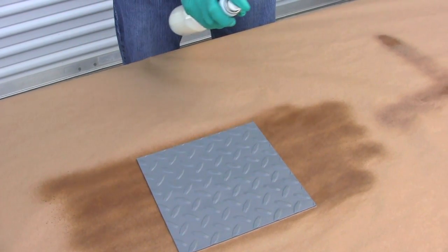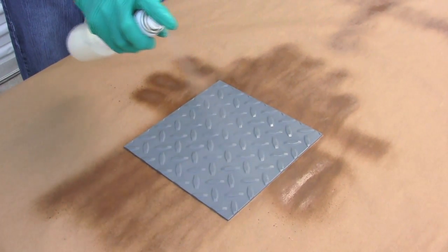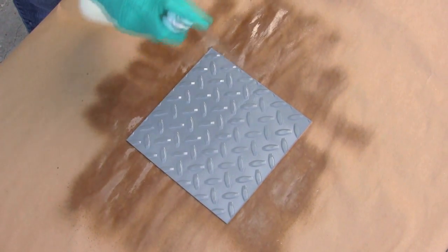Maintaining some agitation by swirling the jar during the application is recommended. Do not shake the jar when it is attached to the power unit. Keep the sprayer between a 90 and 45 degree angle. Maintain a proper distance and keep the sprayer moving to avoid wetting or pooling.